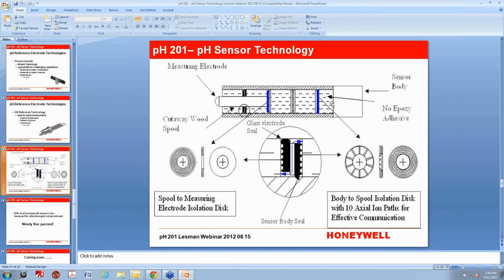So let's say you put this technology next to any of the other ones in, say, a lime scrubber in a power plant. I did a test with it when we first came out with this, and it was first against the Great Lakes in this application. The Great Lakes was lasting 2 weeks. Then we put in what we call our Meridian, which is a gel-filled reference. The Great Lakes was a differential. We put in a gel-filled, and it lasted 4 weeks. We put in a DuraFet, so then we switched from the glass to the FET, but still a gel reference, and that one lasted 6 weeks.